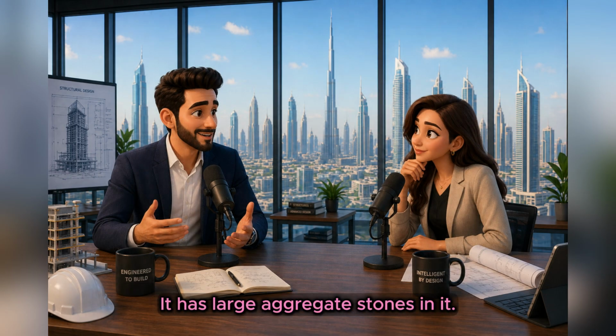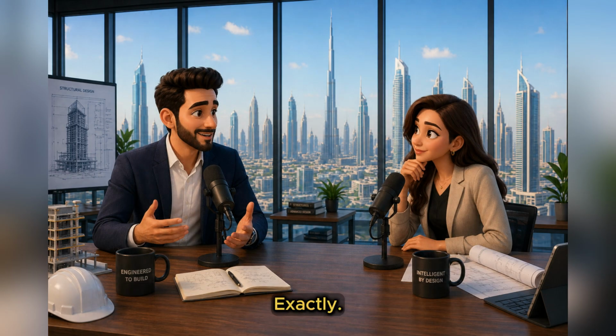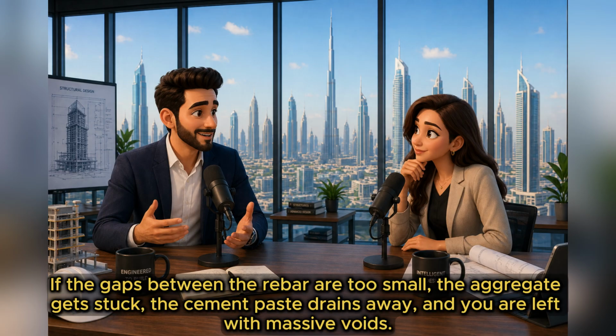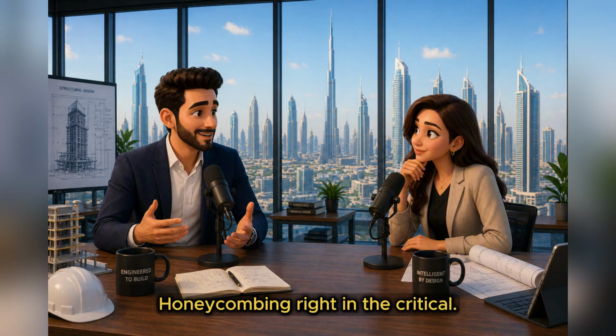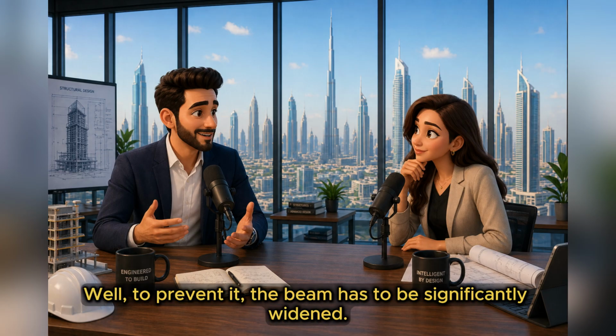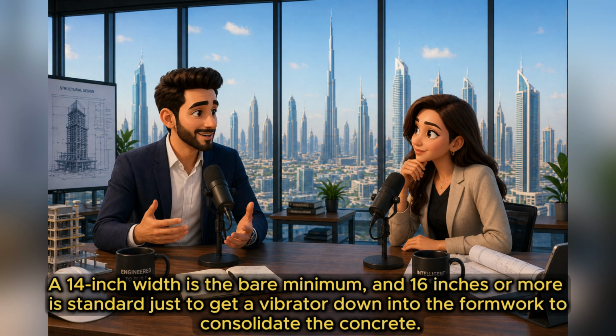It practically is. And remember, you have to pour wet concrete through that. And concrete isn't just liquid. It has large aggregate stones in it. Exactly. If the gaps between the rebar are too small, the aggregate gets stuck, the cement paste drains away, and you are left with massive voids. Honeycombing. Right. Honeycombing right in the critical center of your beam. So how did they try to fix that? Well, to prevent it, the beam has to be significantly widened. A 14-inch width is the bare minimum, and 16 inches or more is standard, just to get a vibrator down into the formwork to consolidate the concrete.